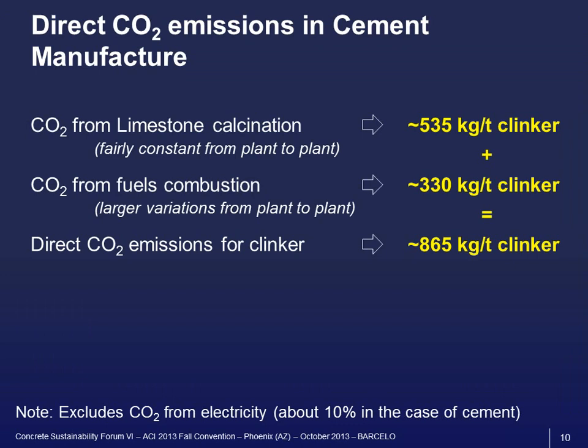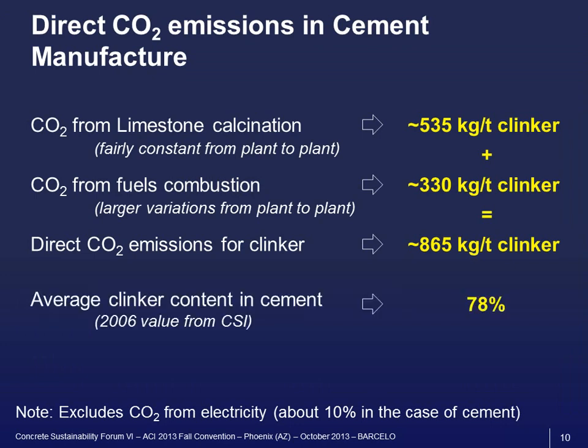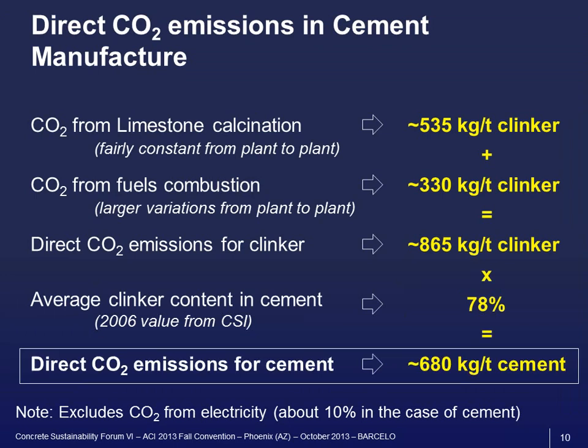And this excludes the CO2 from electricity, which is the indirect CO2 emission. But we know that in the case of clinker and cement manufacturing, it's rather small, about 10% of the total CO2 emission. We also know that cement is not 100% clinker. In 2006, CSI made a survey, and they found that the worldwide average was 78% clinker in cement. So when you multiply these two, you have the direct CO2 emissions for cement manufacturing, which is about 680 kilograms of CO2 per ton of cement.